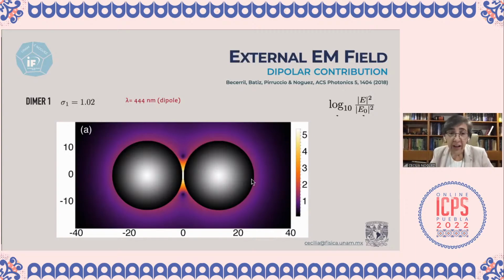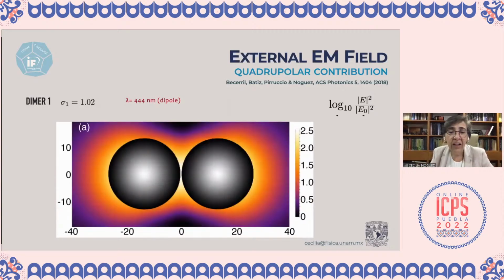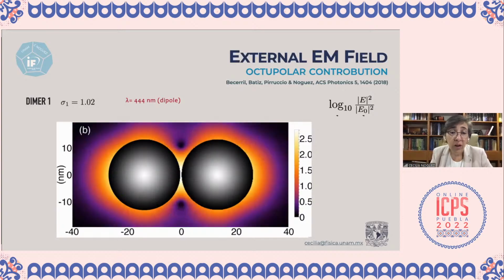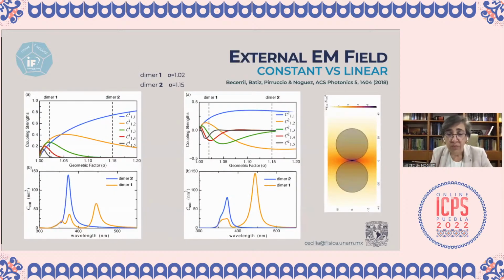So we can modify in this way the response for the dipole just by changing the separation between nanoparticles. And also we can have these different kinds of contributions that come from the quadrupolar contribution that are excited because of the presence of the second nanoparticle, or an octupolar one, okay, and so on.